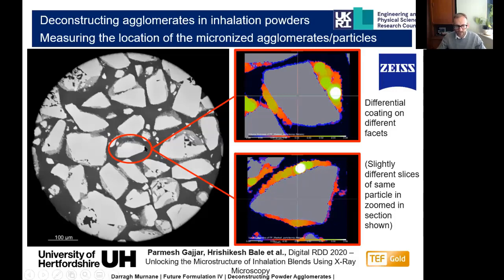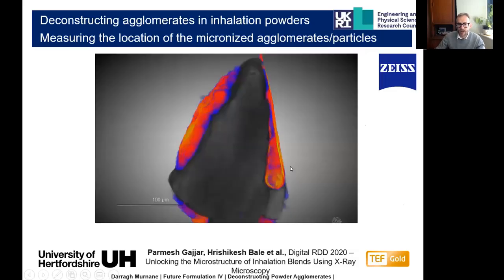So our X-ray microscopy has been able to reveal where it is that the drug is distributed throughout the blend, but it's also able to look at microstructural effects, such as the interaction of drug on the surface. And we can digitally remove the rest of the formulation from the image, and we can look at a single tomahawk, these typical tomahawk shaped crystals of lactose monohydrate. And on these particles, we're able to see the face-specific binding now of the drug phase much more clearly.